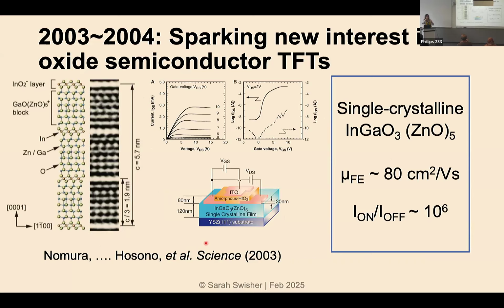And they have this sort of superstructure where they've got the indium oxide layer and then the gallium zinc oxide layer. And using this material, they used PLD to deposit the film, and then they actually annealed it at about 1400 degrees to get this crystalline structure. And when they did that, they got a field effect mobility of about 80 centimeters squared per volt second and an on-off ratio of these transistors of about 10 to the 6.